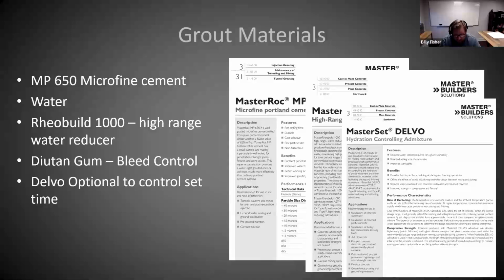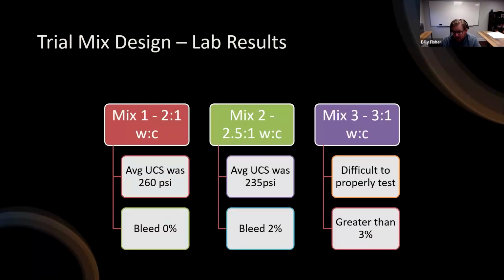Grout stability can be described in two ways, through bleed, and then Diutan Gum was a sugar byproduct, which means we had to be careful we didn't overdose it, because it can adjust the set time. The Diutan Gum was a powder, so we had to mix it with water to make it into a gel prior to adding it to the mix.